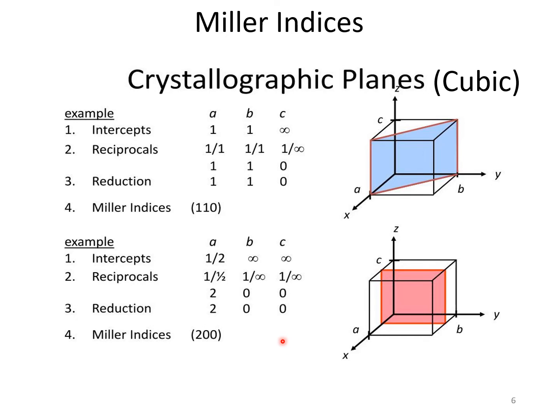So basically, when it comes to crystallography, you don't have to do all these intercepts. You can do it in your head easily. But for simple planes like this, for instance, the 100 would simply be this plane here. 200 is our planes that are spaced halfway along the unit cell.